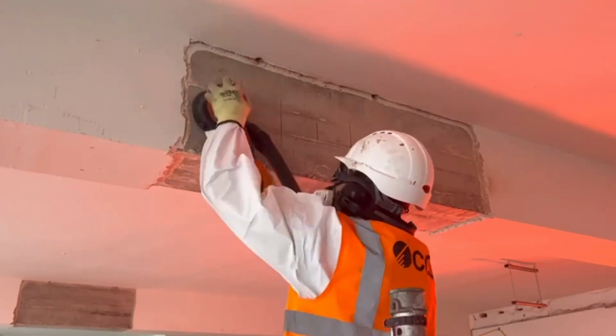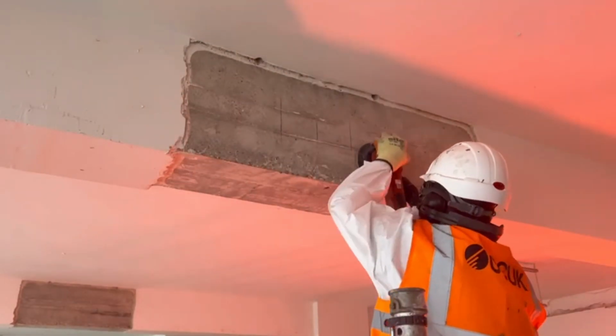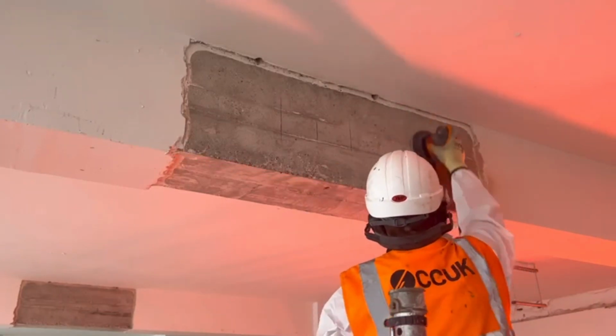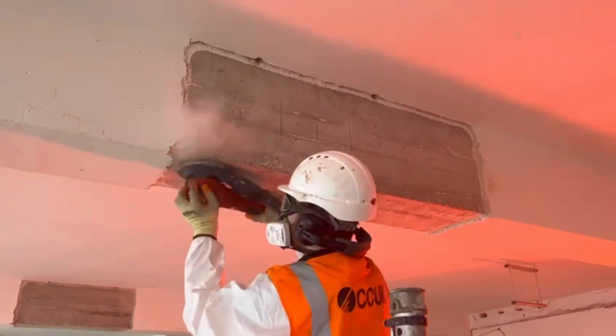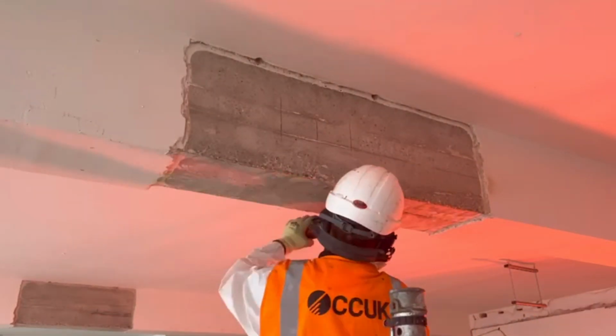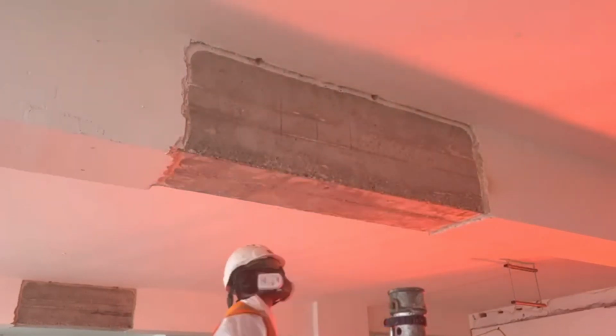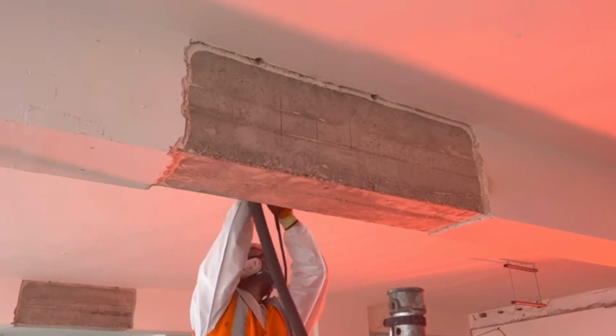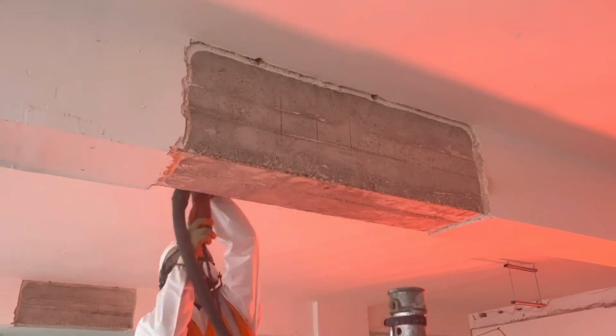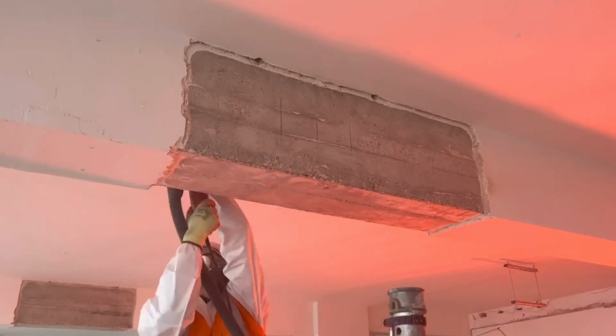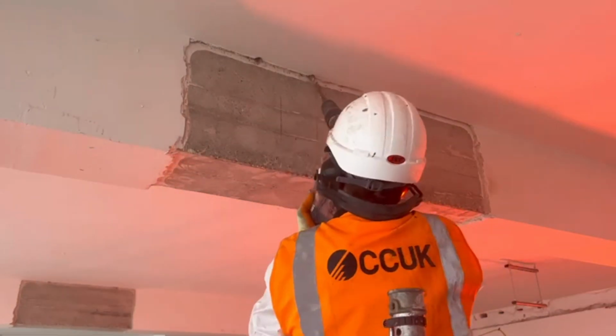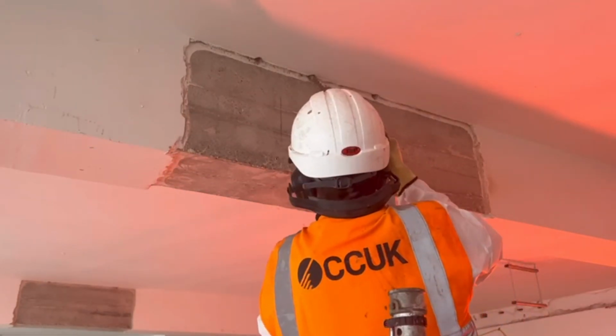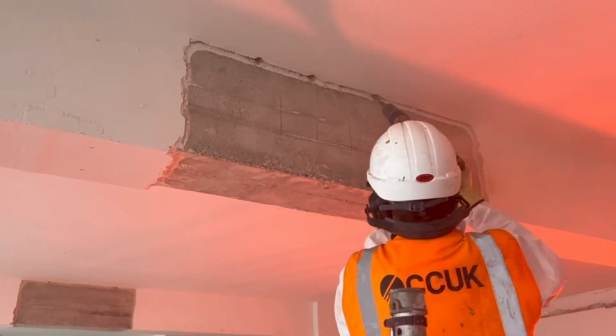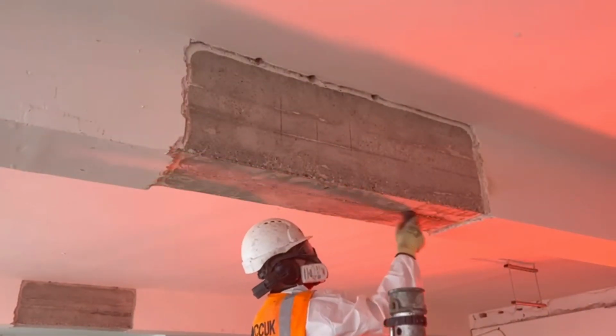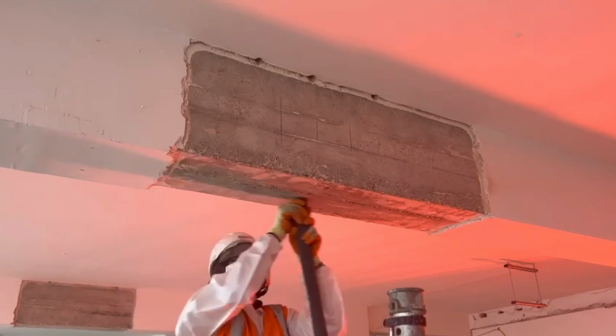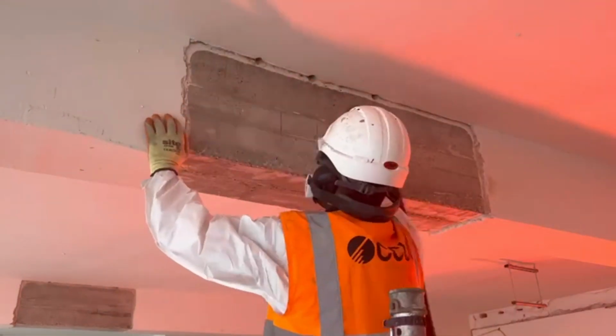So we're going to see the video of the application process itself, yeah? Yeah, so the first thing is surface preparation, which is done by diamond grinding. Usually the plaster was removed by the main contractor, then we drill holes for the carbon fibre anchors into the beam and slab junction so that we have continuity there. Then they grind the area and clean it, so it needs to be dust free. And then once that's been done, they can continue with the application.